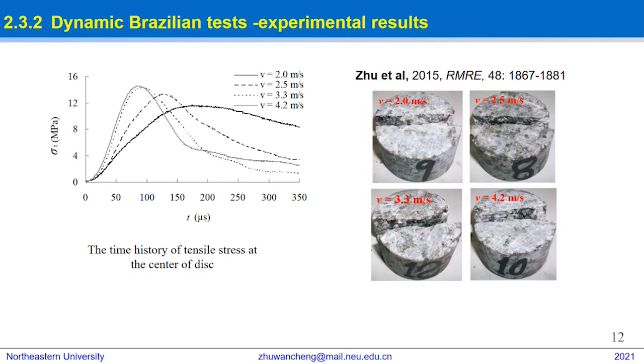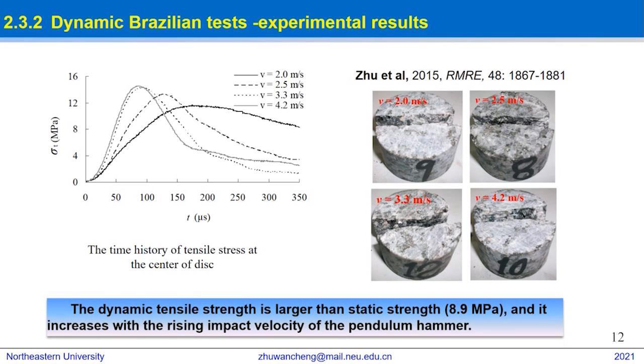The figure on the right shows the failure patterns observed during the laboratory tests with the pendulum hammer-driven SHPB apparatus. Our results show that the dynamic tensile strength is larger than the static strength, 8.9 MPa, and it increases with the rising impact velocity of the pendulum hammer.